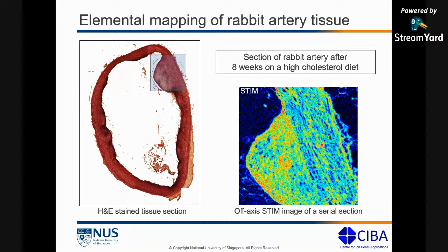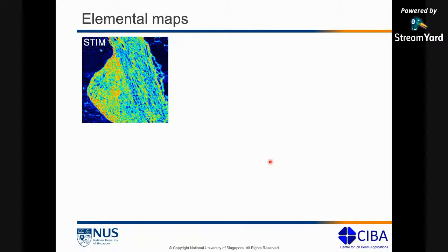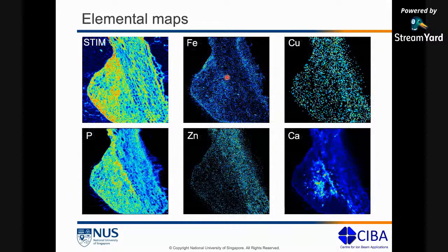Just like I said to you before, when we do off-axis STIM imaging, we also collect PIXE signals as well. So we are collecting X-ray signals at the same time. From the X-ray signals, we are now able to identify which elemental peaks are present in your sample. If we select these elemental peaks from this off-axis STIM image, we can get these different elemental maps. We have an iron map, a copper distribution map, a calcium distribution map, zinc, and phosphorus. They're all from the same section, but now you have elemental distribution coming out from the sample.